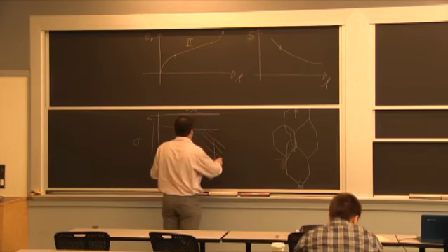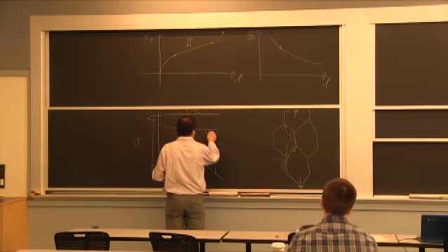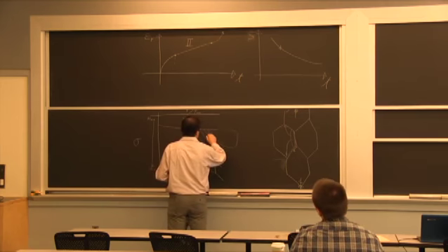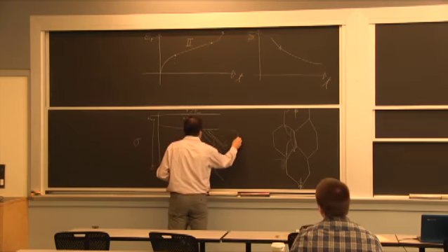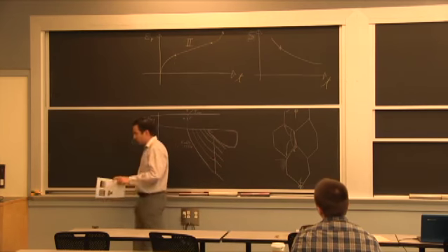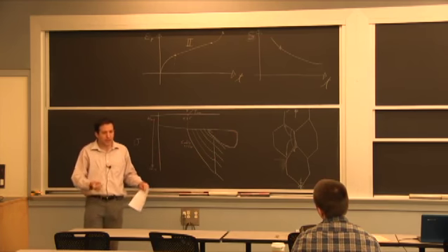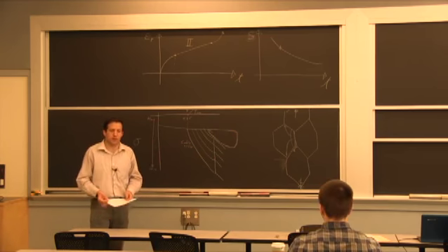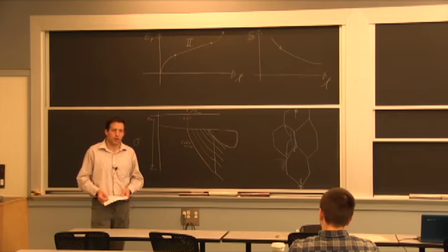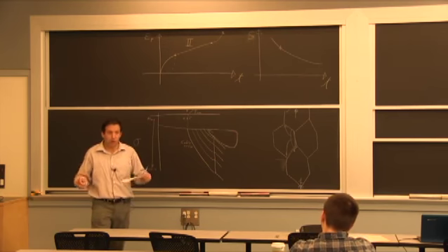There's a third regime that's around here with higher stress. And this becomes a little closer to what happens during a tensile test. You have the dislocations that participate in the deformation, with the difference that you also have a recovery of these dislocations.